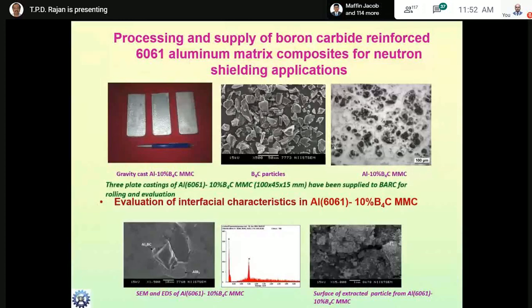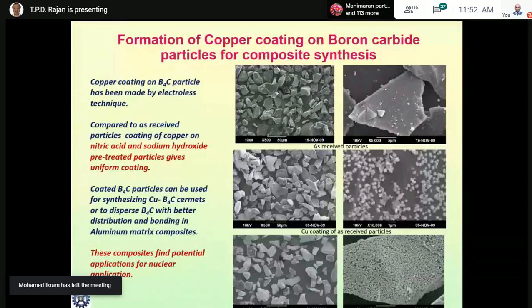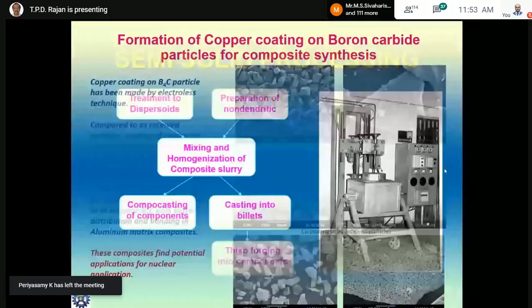So they disperse the boron carbide particles, and this has been used to make boron carbide dispersed aluminum composites for neutron shielding applications. And this is about the coating of reinforcement to have a better dispersion in the matrix. Electroless coating is used, and this is under different conditions.